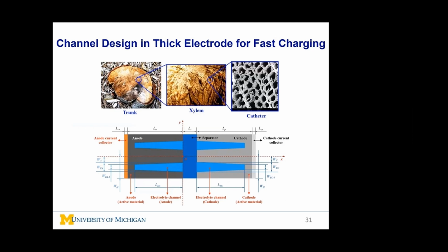We further applied machine learning approach for design of battery channels. To increase the specific energy, using thick electrode can help. However, with thick electrode, the diffusion of lithium ions will be reduced because it has to diffuse through a larger thickness. To facilitate lithium ion diffusion, motivated by what we observe in nature, such as trees, which deliver nutrients efficiently, we can create channels in the electrode so that the lithium ions can move quicker through the channel and infiltrate the electrode.